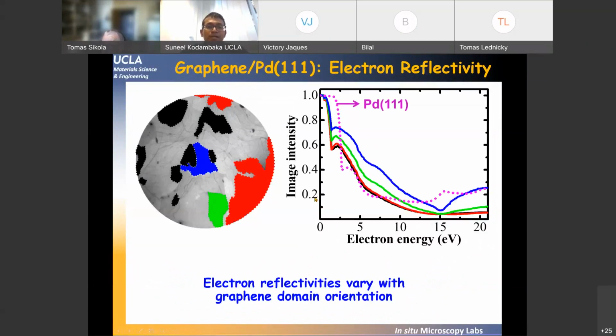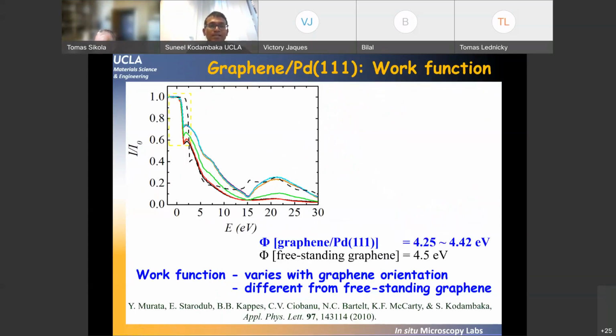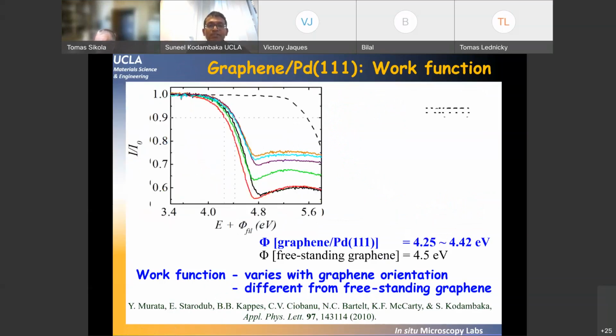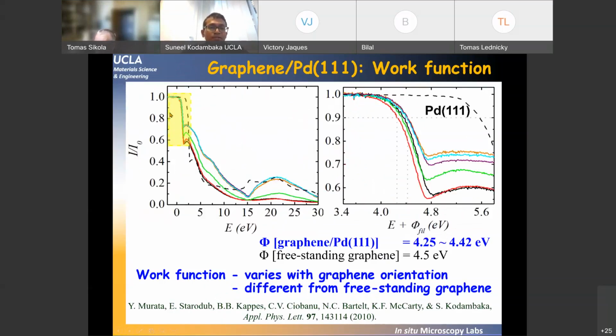Okay. Now here, I have done the same type of measurements, but now in more localized regions. These three different colors correspond to three different domains of graphene. And for reference, I'm also plotting the reflectivity of clean palladium 111 surface. And what you see here is that each of the domains has slightly different electron reflectivity behavior. Now let me focus on the low energy region, within 5 eV or less. I've just magnified the image intensity, normalized to the initial intensity of the image, as a function of electron energy.